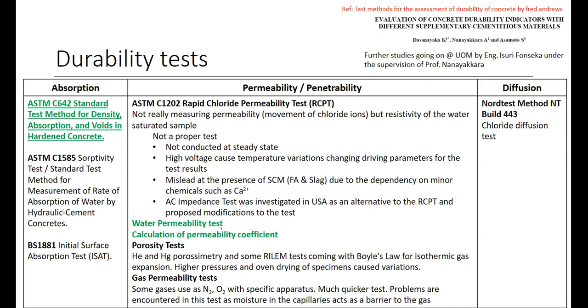So an AC impedance test was investigated in the USA because they also identified that the test method is not good, it's not accurate. So they are also in the process of developing alternative test methods instead of using RCPT. Now they are working on a proposed modification for the test. Another one is the water permeability test, which calculates the permeability coefficient with Darcy's law. This is also a good test in terms of permeability.